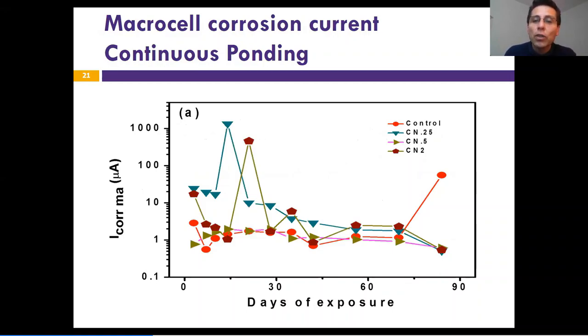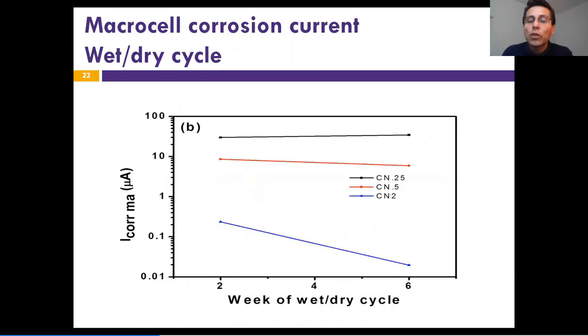So you see the control has a certain corrosion rate, but based on the 2% of the microcapsules, we drop the corrosion rate and it's almost very low. It's a very low level, and 0.5 is also better than the control. So it's very important to see not only the thermodynamic approach, but also the kinetic approach. You see that the control starts to increase the corrosion based on the time. Why? Because we pass from stage one to stage three. But in terms of adding the microcapsules, at the different concentrations, you see how the corrosion rate is decreasing. This is very important, because based on different concentrations, the higher the concentration, the better the corrosion rate for these samples.